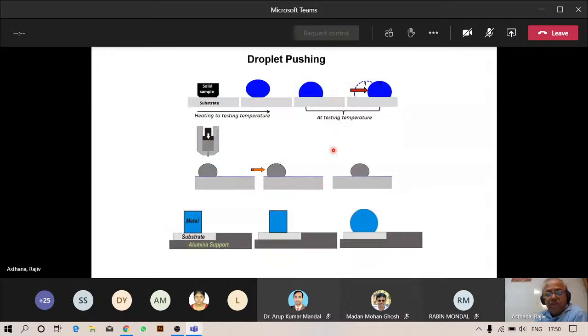One other thing we tried was droplet pushing. If you have a contact heating process, you start with a solid metal on a solid ceramic substrate, let it melt, and then mechanically you push the droplet from one region to another region and open up this interface. You can do the same thing with capillary penetration, squeeze out the liquid, and after a set amount of time, you can push the droplet from one region to another region and open up the interface.